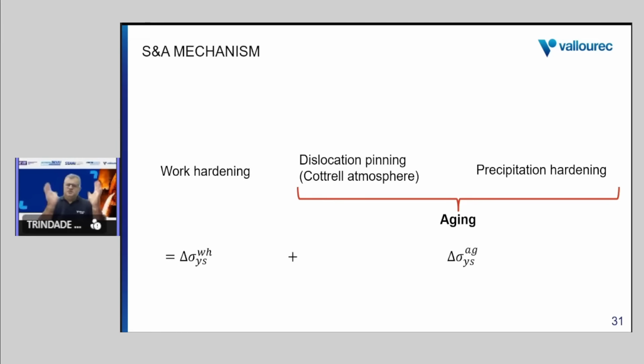So based on all this theory and our experimental observation, we could conclude that work hardening is, of course, very important. The most important increase in strength after strain and age is due to work hardening, around 70 to 80%. The other 20 to 30% is due to aging. What we could demonstrate is that this aging most probably is not dominated by precipitate hardening, because we could not identify any big difference in the precipitation pattern after aging. Most probably the aging contribution is dislocation pinning, I mean, the Cottrell atmosphere saturation.